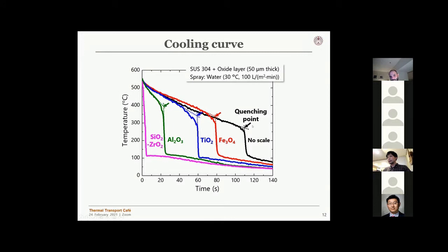We can define the quenching point here. This line corresponds to the film boiling regime, and this steep temperature drop corresponds to nucleate boiling, so the quenching point is here. With oxide layers, the quenching point increases. In this case it was just below 300, but with an oxide layer it's just around 350, and even 400.